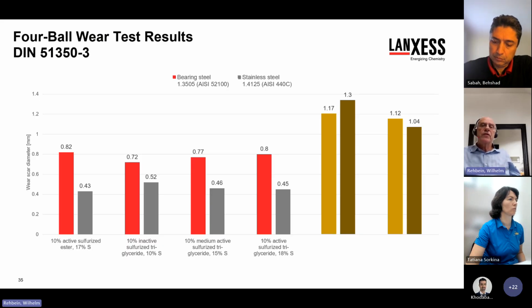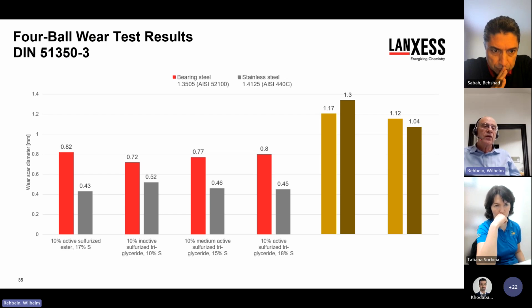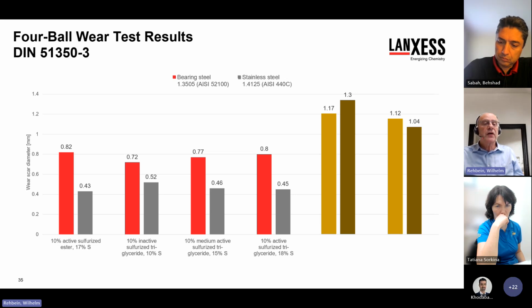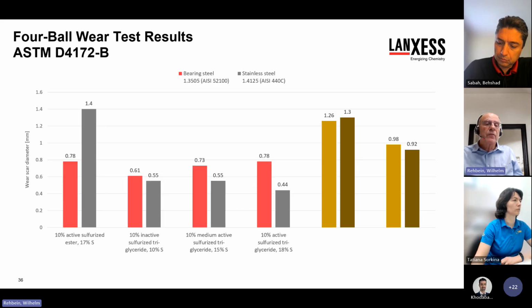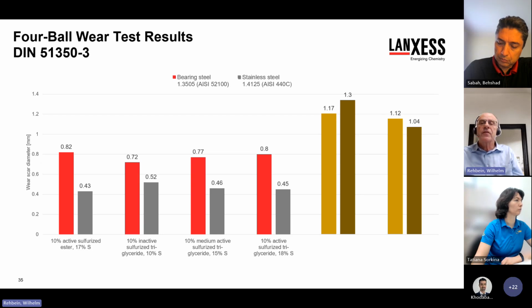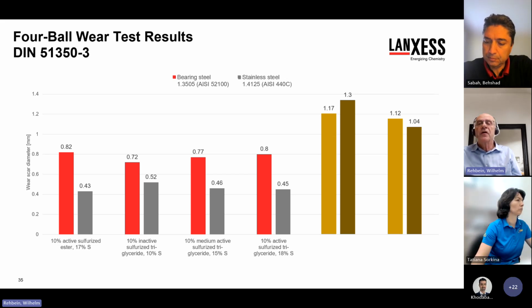When running the test according to the DIN standard, we found the lowest wear scar diameter on bearing steel with the inactive sulfurized triglyceride, which is 0.72. With the more active sulfur carriers, the wear scar diameter was slightly larger. With stainless steel, the gray bars, the effect was reversed. So the wear was reduced with increasing sulfur and active sulfur concentration. But in any case, the wear was significantly lower when compared to 10% or even to 20% medium chain chlorinated paraffin.